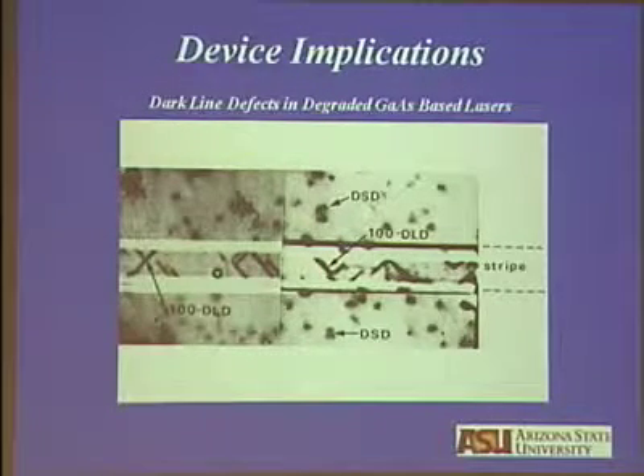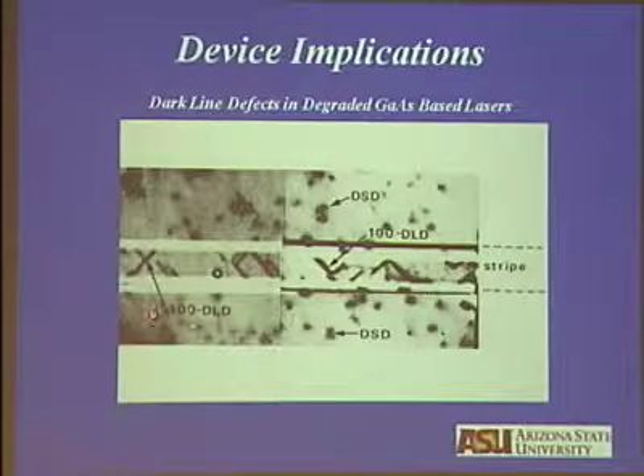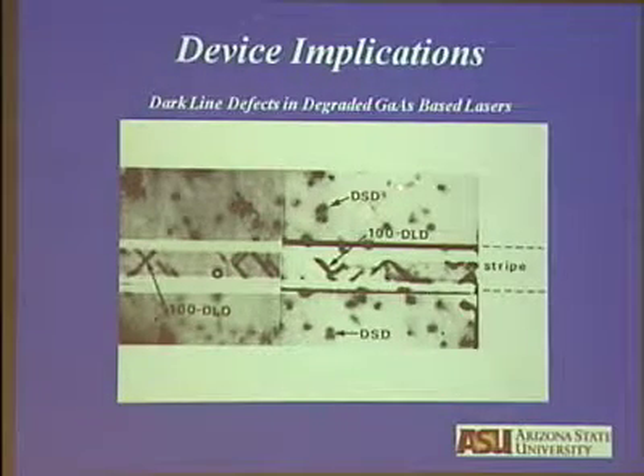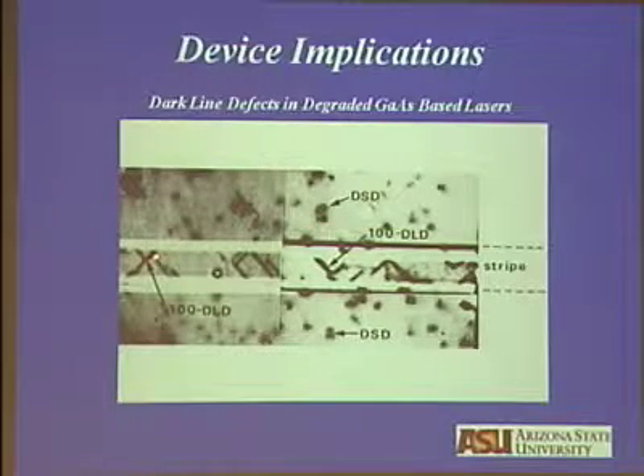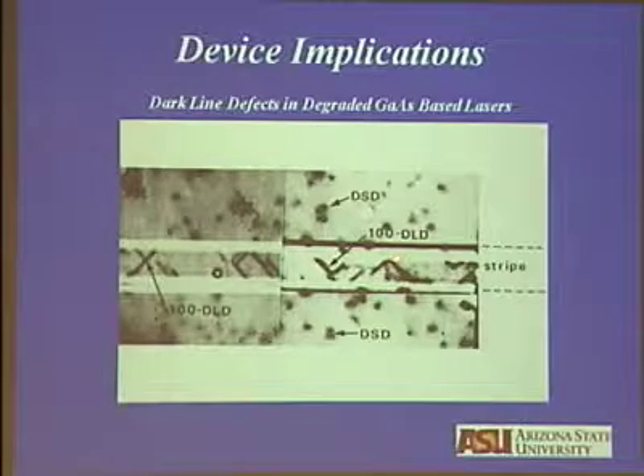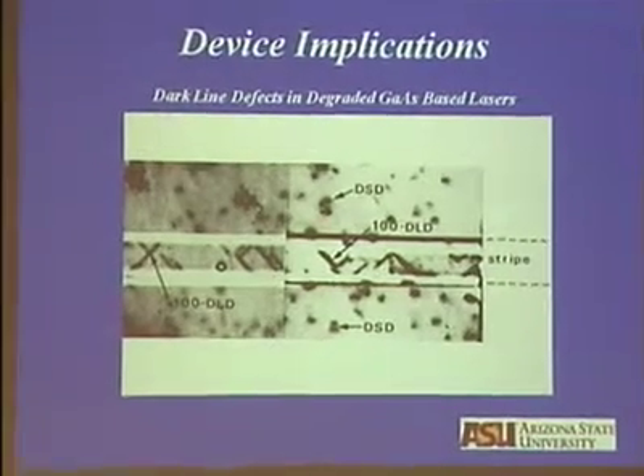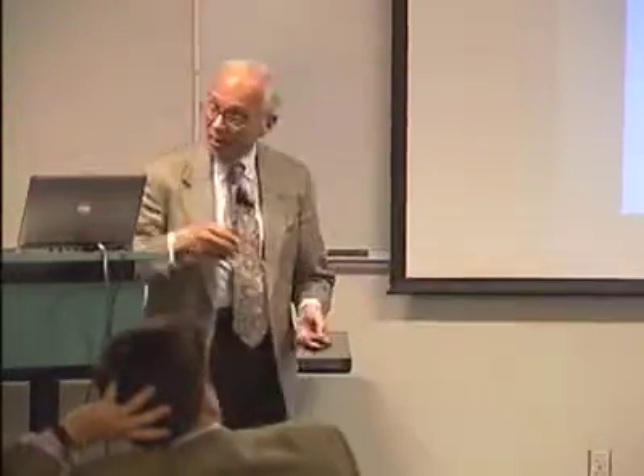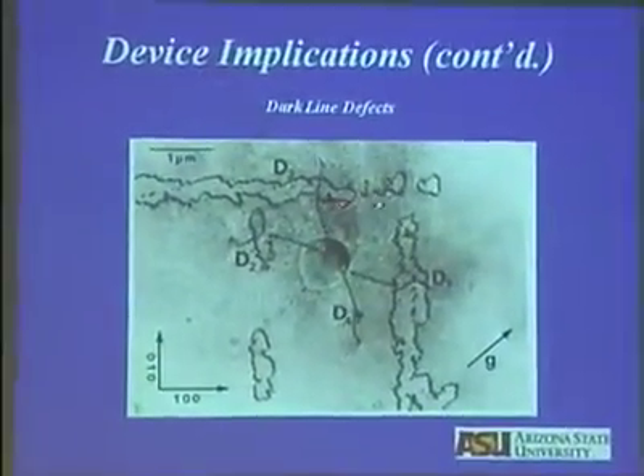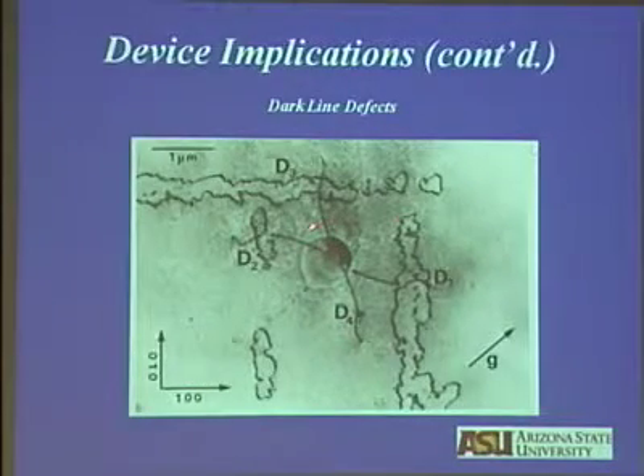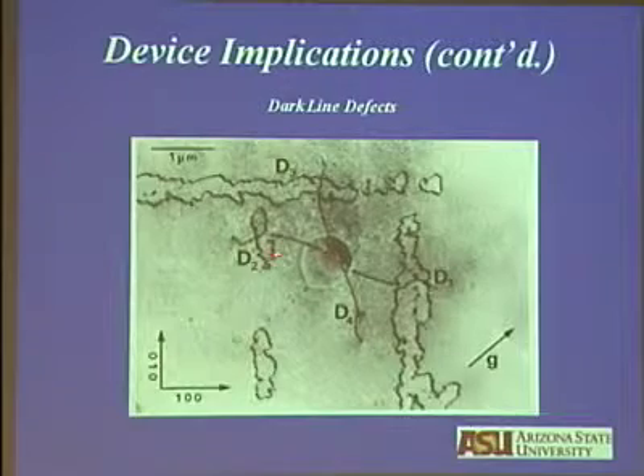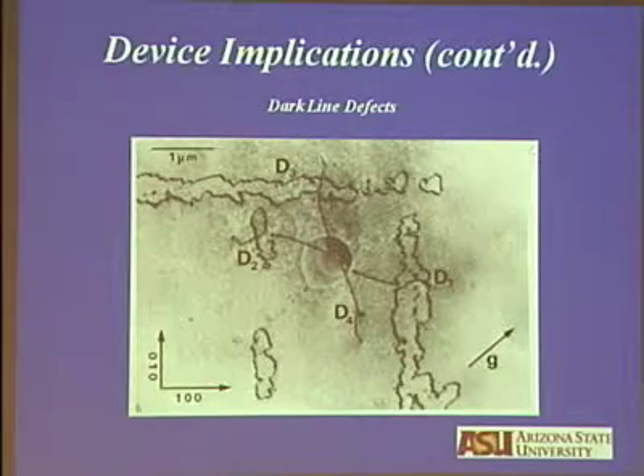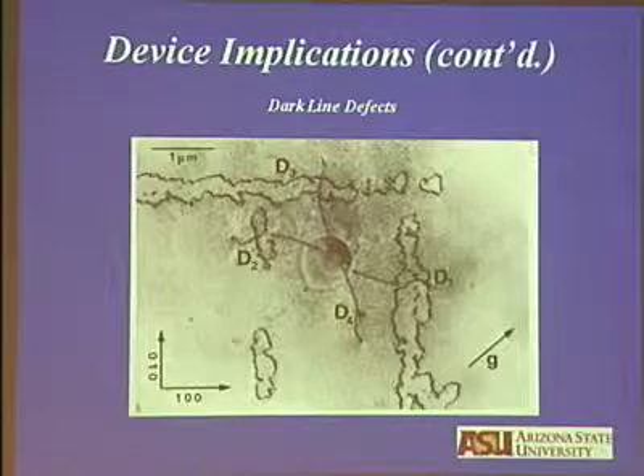But with the operation of the laser, you develop these dark lines. Don't worry about the dark spot defects that's shown here, that's due to the indiffusion of metal into the layers, but these are the important ones, the dark lines. What happens is the device dies. They develop these dark lines into the structure, into the active layer of the device, and it dies. Now look at those dark lines, and what you see is, those who do dislocation theory will be enamored. This is dislocation in the layer. It multiplies, highly crinkled, showing that climb is occurring in these materials, in the development of the dark line defects.